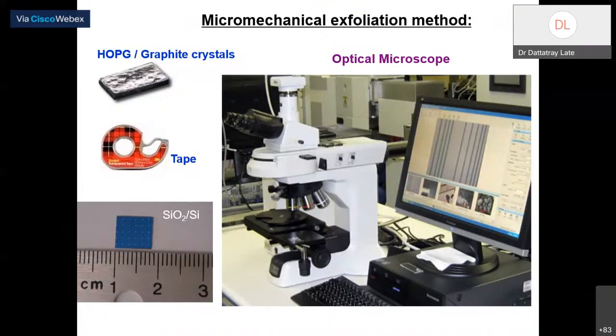So what do I need? I need this graphite crystal. I need this magic scotch tape, which is available in the market for 5-10 rupees, and I need an SiO2 Si substrate. And I need a simple optical microscope, which is available in any biology laboratory in your institute. I particularly need 300 nanometer thickness of SiO2. Any thickness is fine, but 300 nanometer SiO2 gives very bright contrast for these graphene sheets on your substrate.